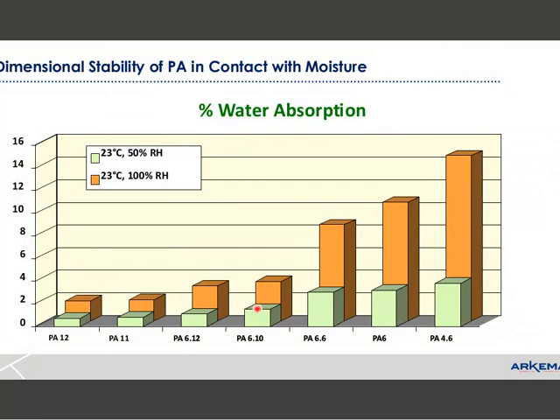Water absorption on the long-chain polyamides, we're looking at 50 and 100% relative humidity. What you can see is that these long-chain polyamides have very, very low moisture absorption compared to other polyamides. And so in this case, the water absorption is maintained at 50% RH, well below 1.